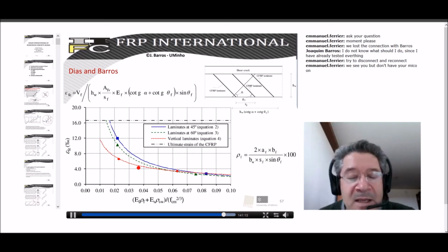From the extensive data that we collected, we realized that effective strains decrease with the stiffness of the FRP, with the percentage of existing steel stirrups, and also decrease when we adopt a lower strength concrete class. And this is the type of evolution in terms of the effective strain with these parameters.